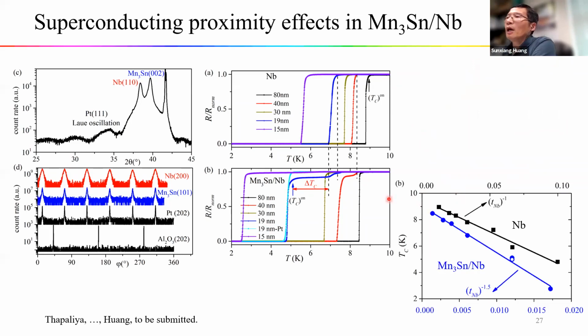So if we plot the TC as a function of the thickness, for a single layer of niobium, the TC is inversely proportional to the thickness. But for the bilayers, the dependency is like the thickness to the -1.5 power. So this result shows a very strong proximity effect in these systems.